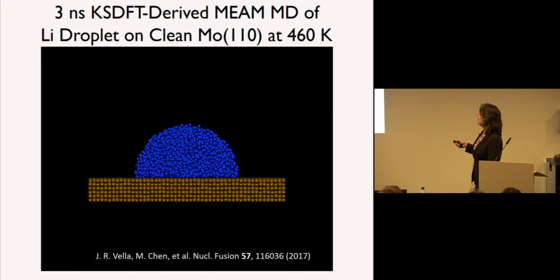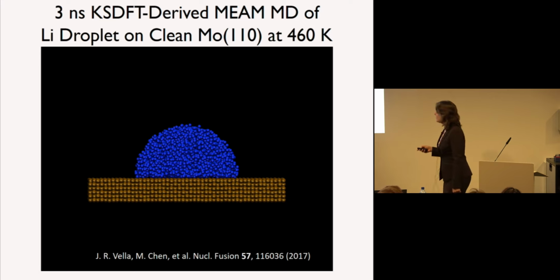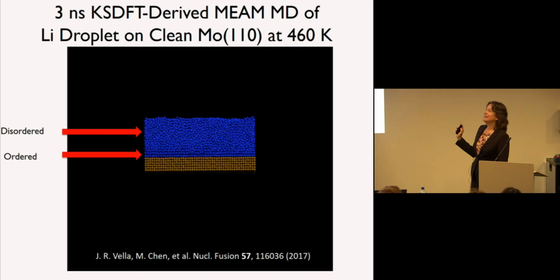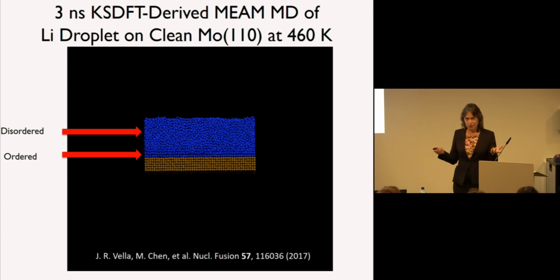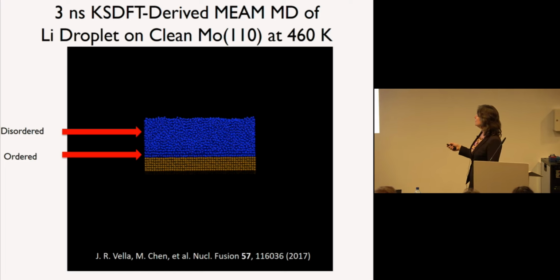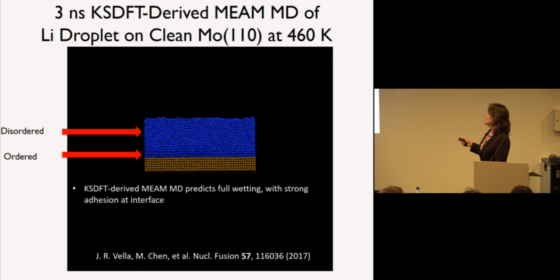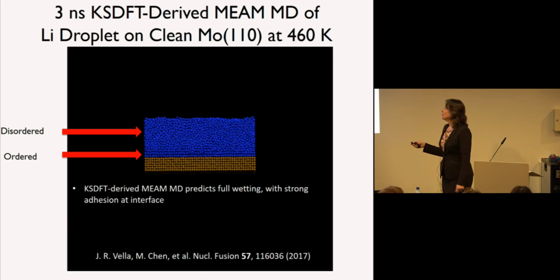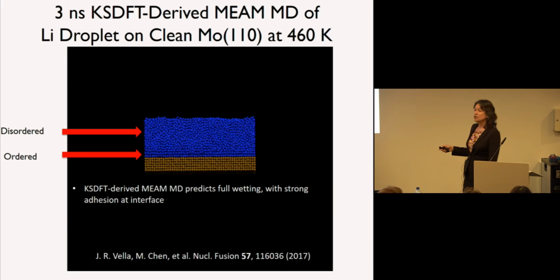It's on a clean molybdenum 110 substrate. And I'm just showing you the beginning and the end, okay? And what we find is that because of the relatively strong binding, the ground state lithium at room temperature is body center cubic, as is molybdenum. And so there's an ordered part near the interface, and then there's a disordered part of this droplet. So this first part is essentially trying to layer and solidify a little bit, but then you're left with quite a bit that is disordered and is a liquid. So that's the prediction from the theory, that we predict full wetting with strong adhesion at this interface.